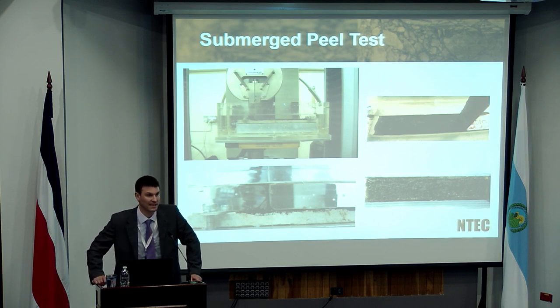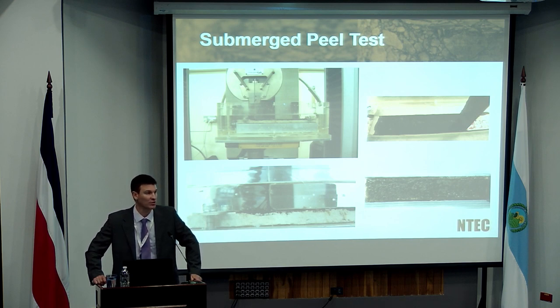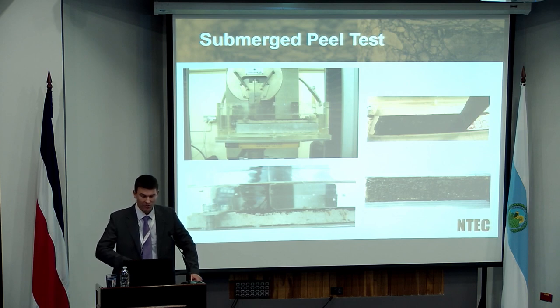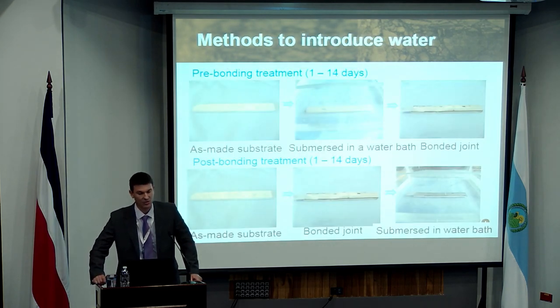There are effects, and I'll show you some of the results in a second. There are effects in that potentially the longer you leave it in water, the more the bond between the aggregate and the bitumen would start to fail. You start to get your effects of adhesive failure and stripping and moisture damage. And also the values of your fracture strength tend to change as well. As you move from a cohesive type failure in the bitumen to an adhesive failure at the interface, you see a reduction in fracture strength. That was the one way of doing it. It was mildly successful, but what we've ended up doing is two other ways.